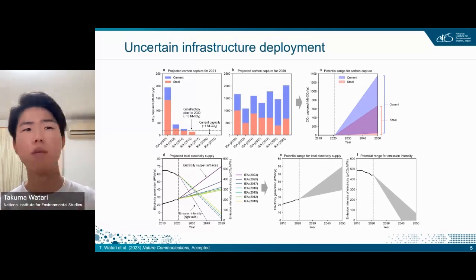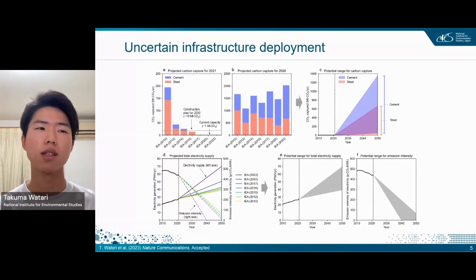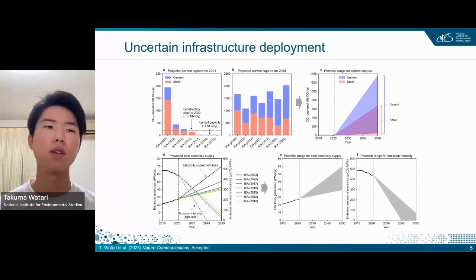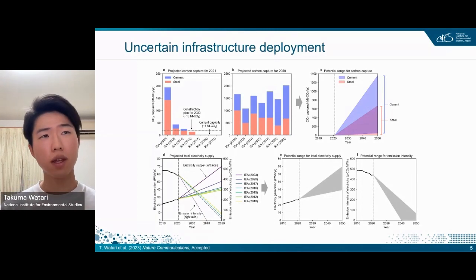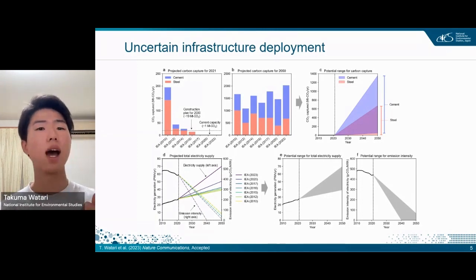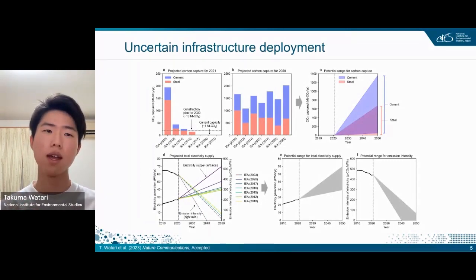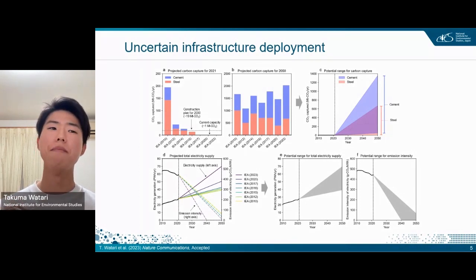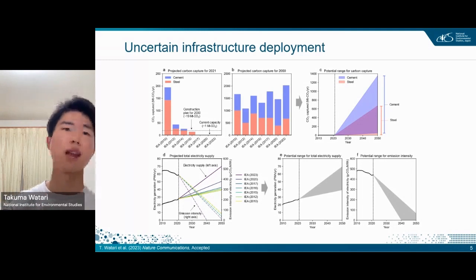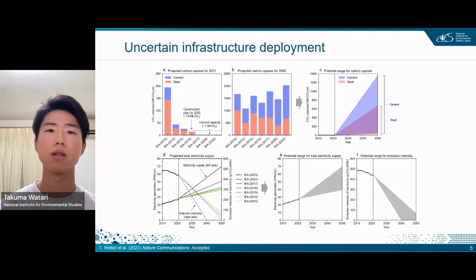And we currently have an almost negligible amount of CO2 capture and storage capacity in the steel and cement sector, less than 1 megaton CO2. But if you look at the 2050 data, we can see that the IEA almost constantly projects roughly 2,000 megatons CO2 to decarbonize global steel and cement production. And that's great, obviously, if we could achieve that scenario within 26 years' time. But the deployment is highly uncertain given the history of failures and the scale of the challenges we have to face. So that's the case of CCUS, or carbon capture and storage.